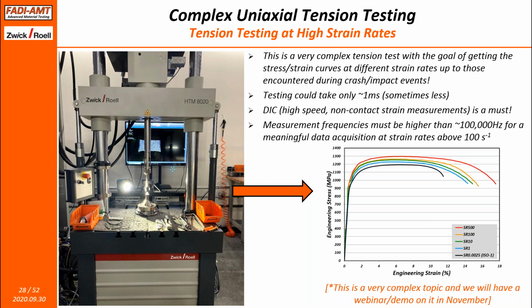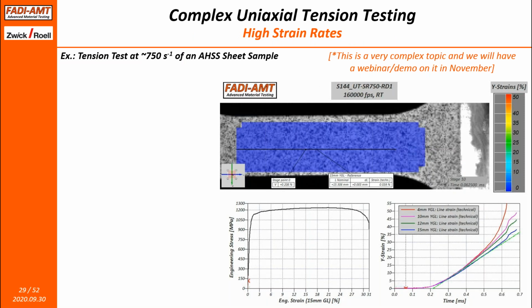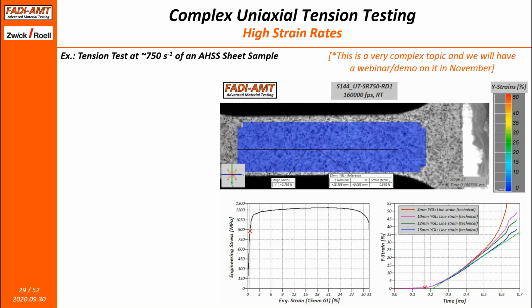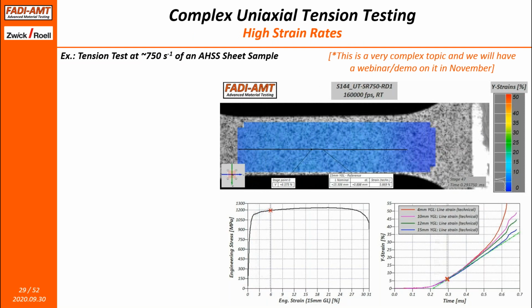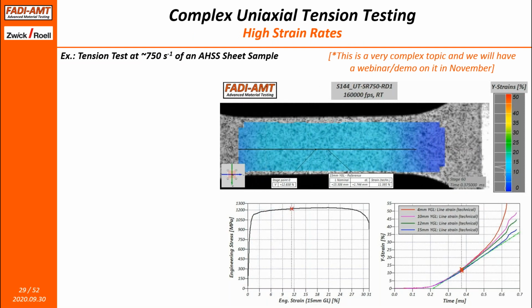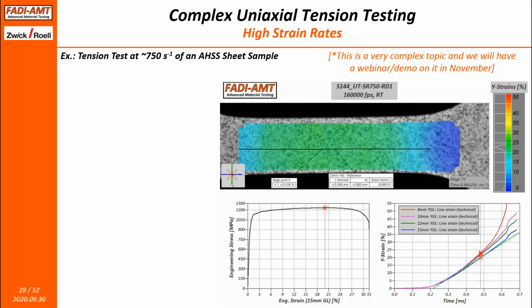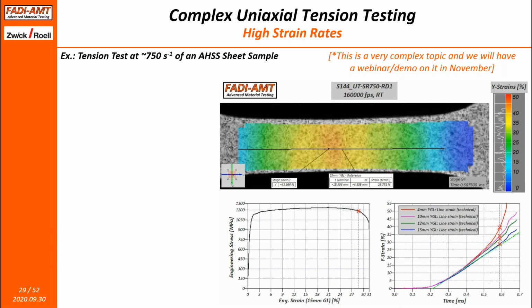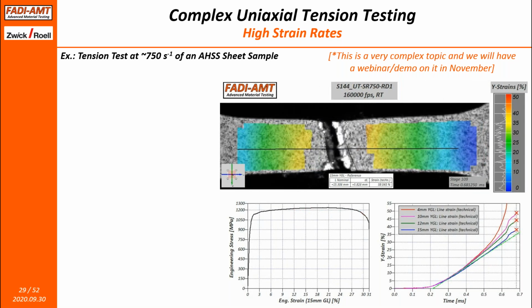So everything has to be non-contact and has to be synced in a very accurate manner with the machine in order to couple the two together in order to get stress strain curves like the ones that you see on the right-hand side. So this is just an example of a video that's taken with DIC, because DIC is nothing but a camera measurement. So if you can replace a conventional camera with a high-speed camera, in essence, you can obtain strains at very high speeds. And that's basically what is shown in this particular video.